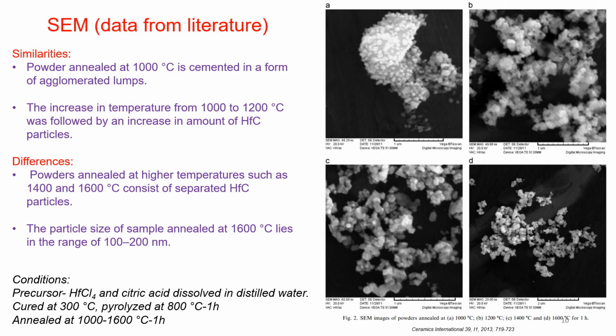These SEM micrographs were then compared with the data from literature. Similar results were observed for the samples pyrolyzed at 1000 degrees C, where we see agglomerated lumps of hafnia and carbon. With the increase in temperature to 1200 degrees C, hafnium carbide crystals start to appear. However, at 1400 and 1600 degrees centigrade, we can see well-defined and separated hafnium carbide particles, which is not the case in our samples. And the particle size in this case was in the range of 100 to 200 nanometers.